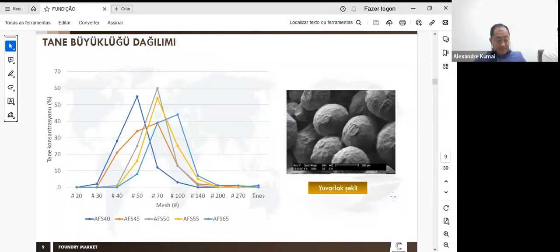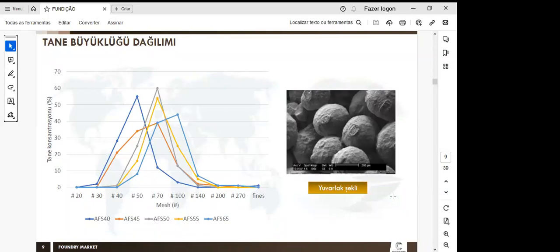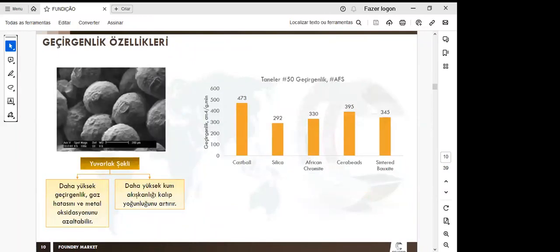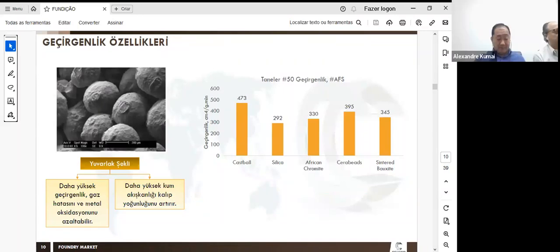Here we have the particle size distribution. These are the typical particle size distribution curves of the Castball. We can offer the sand in the following AFS grain fineness numbers: 40, 45, 50, 55, and 65. Another characteristic is the shape of the grains, which is rounded.